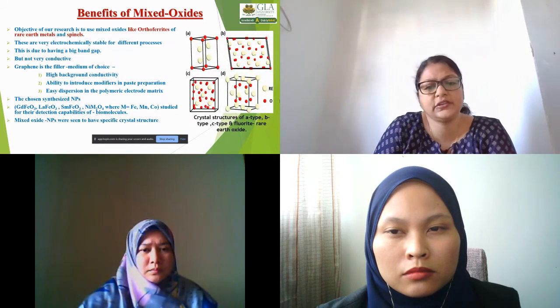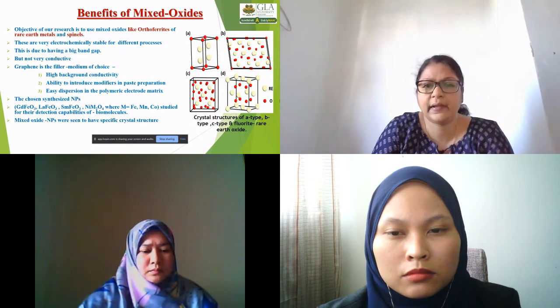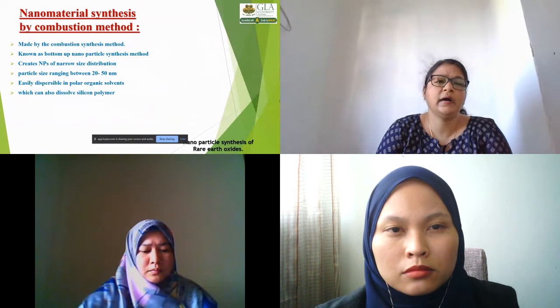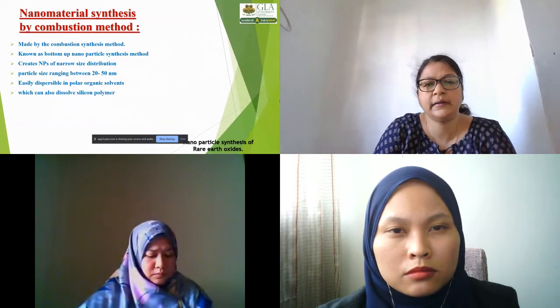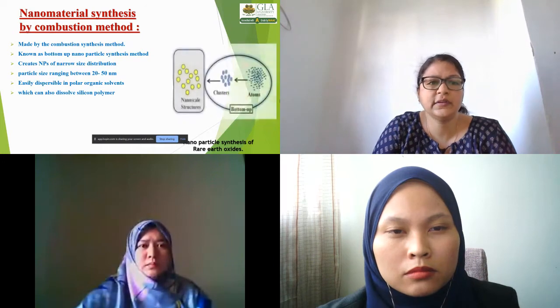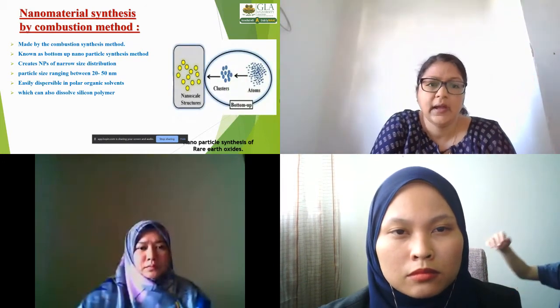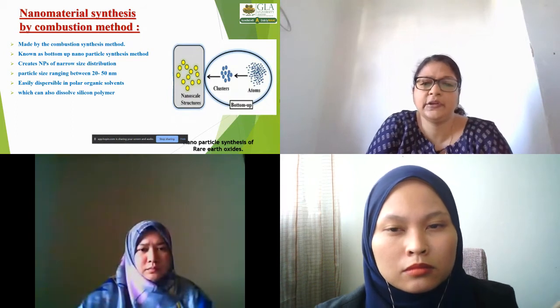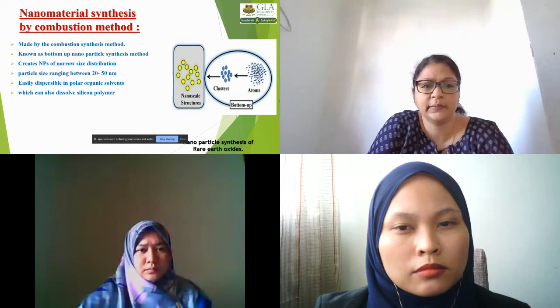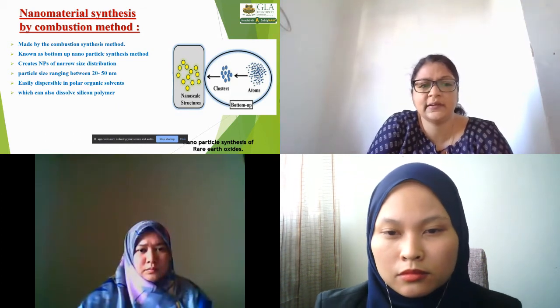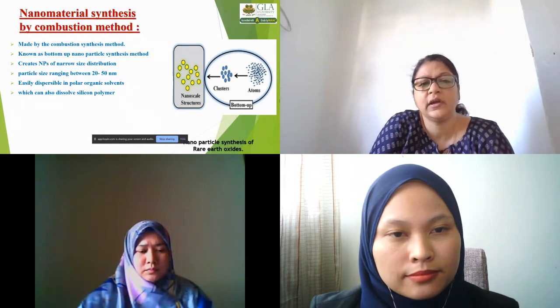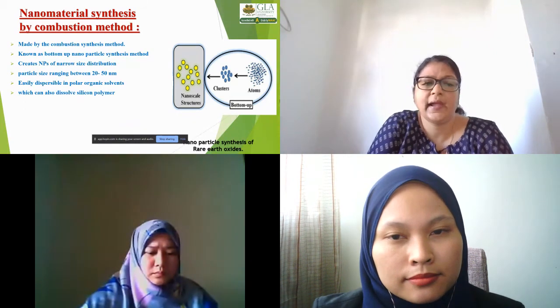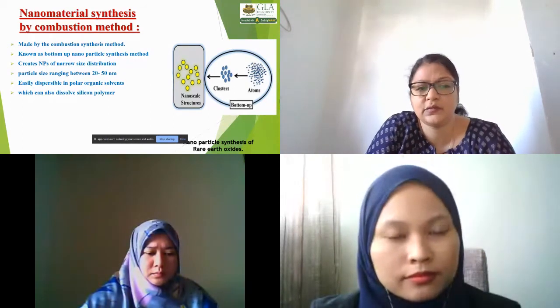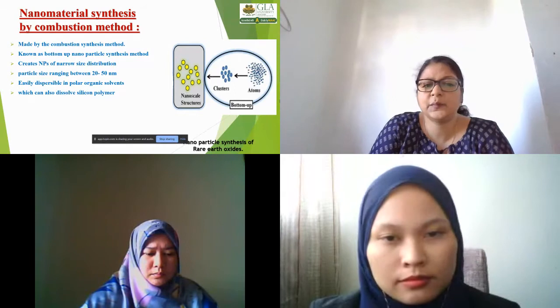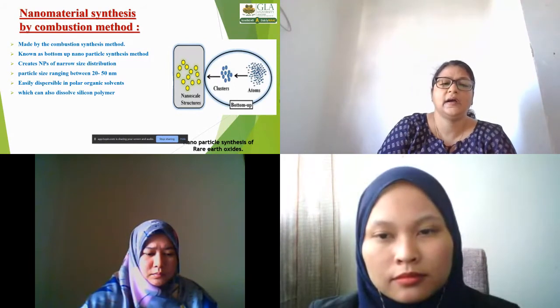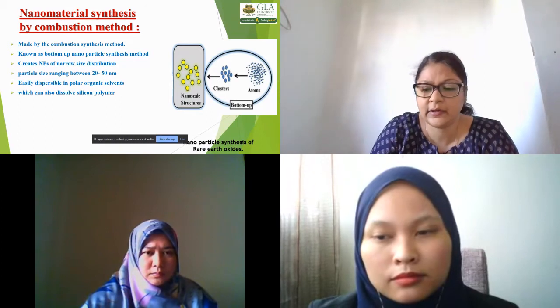These are the crystal structures of these molecules. For the synthesis of these nanoparticles, we used the combustion synthesis method. Generally, nanoparticle synthesis is either bottom up or top down. We use the bottom-up approach as it creates nanoparticles with a good narrow size distribution and small particle size ranging from 20 to 50 nanometers, and they are easily dispersible in polar organic solvents, and dissolve in silicone polymer easily.